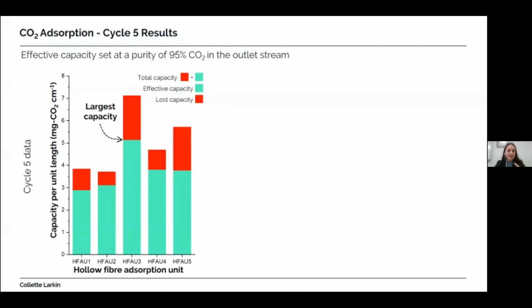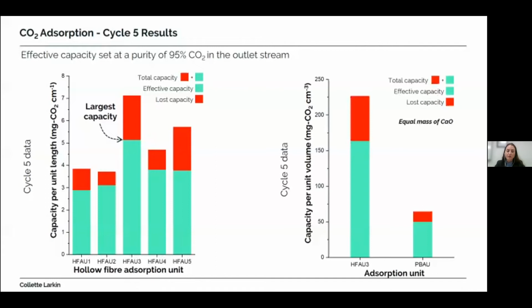Once we obtained this optimised hollow fibre adsorption unit, we were able to compare it against a packed bed adsorption unit that used an equivalent mass of calcium oxide, and we tested it under the same reaction conditions. A particle size diameter of 150 microns was used for the calcium oxide pellets in the packed bed adsorption unit to minimise mass transfer resistances. In this instance, the capacity per unit volume was compared for hollow fibre adsorption unit 3 and the packed bed adsorption unit, as this provides an indication as to which unit can capture the most CO2 whilst occupying a smaller volume. The effective capacity per unit volume for hollow fibre adsorption unit 3 was 3.3 times greater than the effective capacity per unit volume for the packed bed adsorption unit.